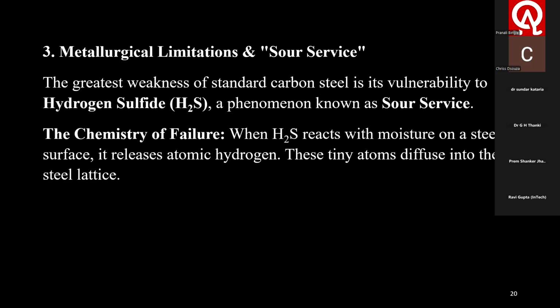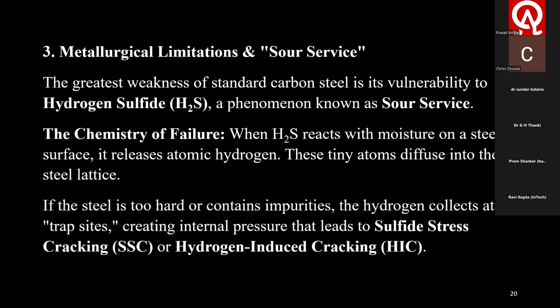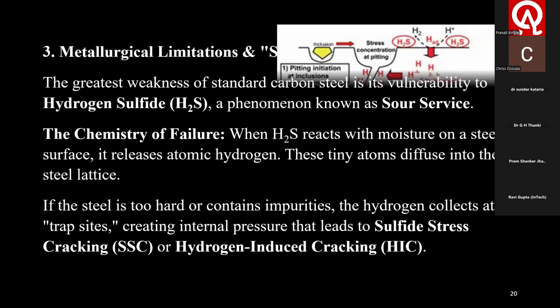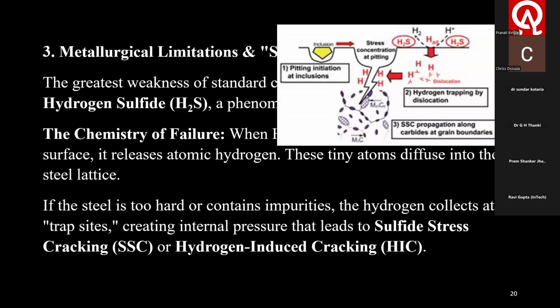When hydrogen sulfide reacts with moisture on a steel surface, it releases atomic hydrogen, and these tiny atoms diffuse into the steel lattice. If the steel is too hard or contains impurities, hydrogen collects at trap sites, creating internal pressure that leads to sulfide stress cracking or hydrogen-induced cracking, like this.